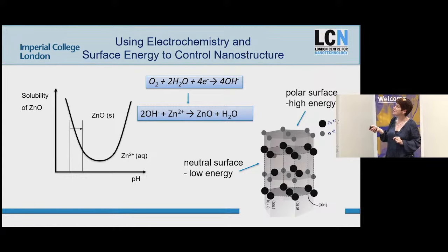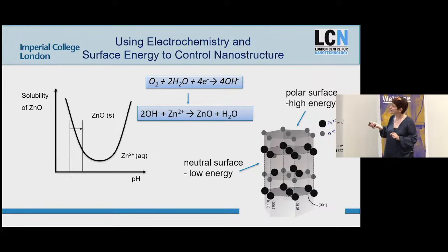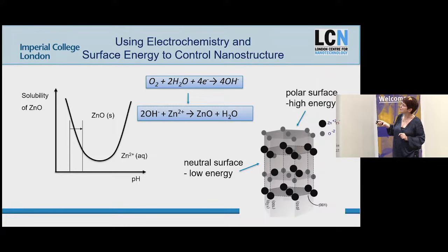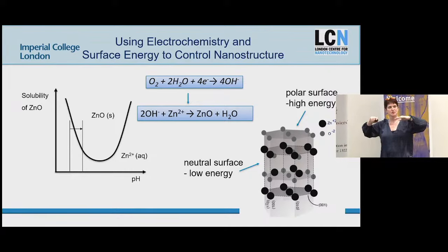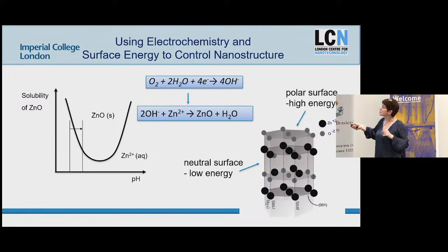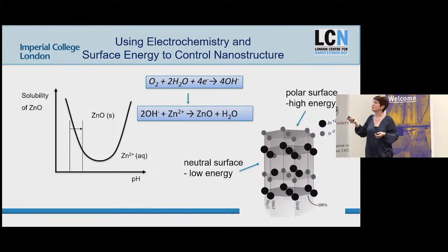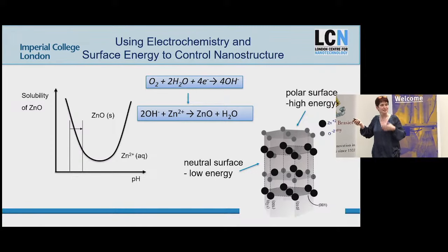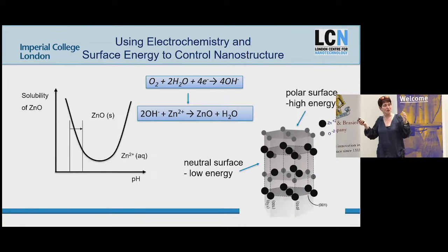The thing you need to know about zinc oxide, it's a Wurtzite structure. That means it's got rows of zinc ions, oxygen ions, zinc ions, oxygen ions, zinc ions, oxygen ions. So if you cut that crystal in this plane, this here, which is now all oxygen, is a very charged surface, right? So you've created a dipole surface. This crystal surface here, positive, negative, is neutral. So the crystal doesn't like this surface, right? It's a charged surface, it's a high energy. So when it grows, it tries to minimize that surface.